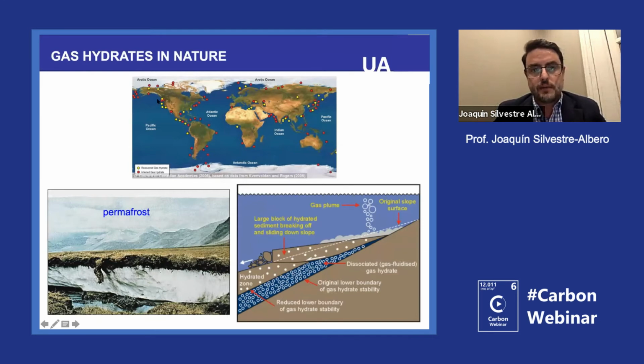Well, if you see the map at the top, in all the continental margins, if you go to the sea and you make a hole, you will find these gas hydrates. Preferentially, methane is the molecule that they are trapping. For instance, you can see here Australia, you have gas hydrate reservoirs, the same in Japan, India, China, United States. So everywhere at the continental side, you have these crystalline structures that are trapping methane. The same happens in the permafrost. So if you go to the Siberian region, you can see that the bottom layers of the permafrost, even though they look like ice, at the end are crystalline structures where you have water molecules encapsulating methane molecules in the center of the cavity.